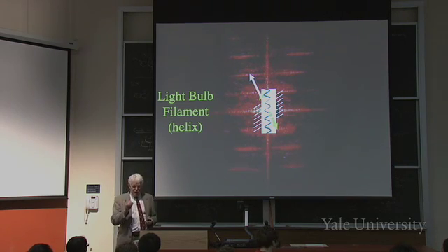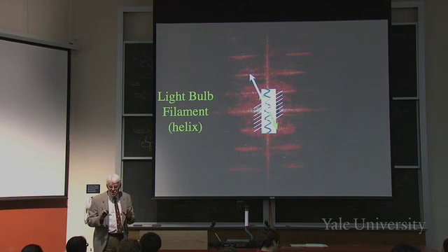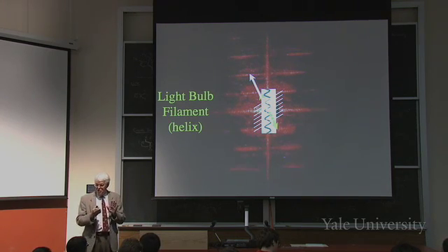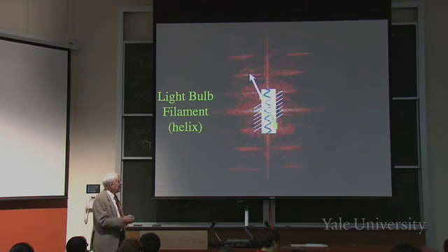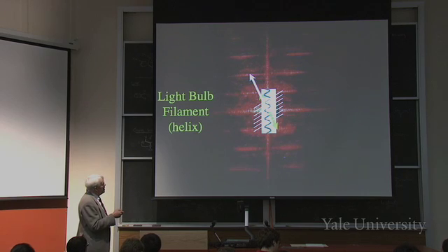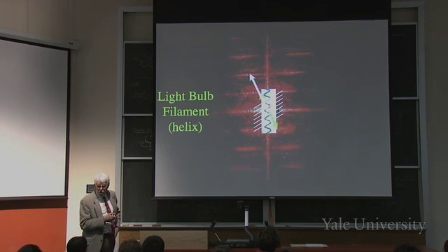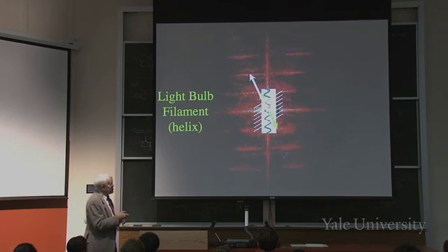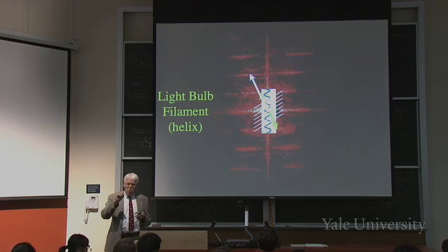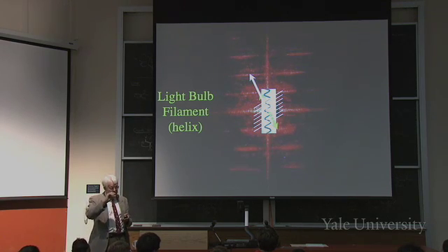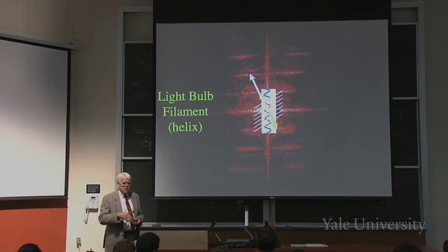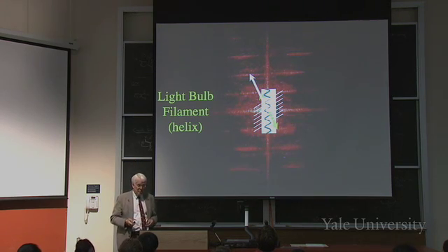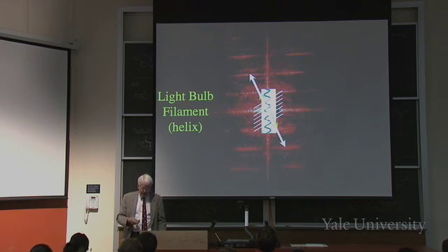And the reason is that there are two things that have to do with the brightness. One is how much density there is on the planes versus how much there is between the planes, right? And we see here that, say, take the original yellow one, all this stuff is nearly on the plane, and halfway between the planes, there's not very much, just a thin cross-section of the wire, okay? But as the planes get closer and closer, the fact that the wire has a finite thickness means that some parts of the wire, the same part of the wire, are out of phase compared to others. So because of the finite thickness, you expect it to slowly fall off in intensity as you go out. But you'll then get the third one along the branch and so on.